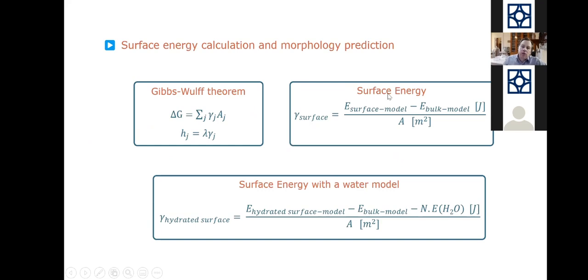So this is how we calculate the surface energies. We calculate them by using the difference, in fact, between the bulk and the surface model, which is mainly the energy you need to cut a surface out of the bulk along a certain orientation, and this per surface area unit, yes? This can be 2 in some calculations, and in some studies you see that there is a 2, because in fact, as you see, when we cut a unit cell in a periodic environment, then of course you have below and above the slab that you create.